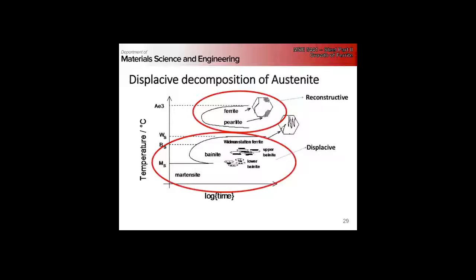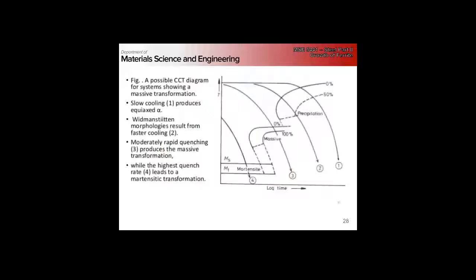So basically, we get this partitioning between reconstructive and displacive transformations, a separation between the nose of the TTT curves here. And if we look at the CCT diagram, here's the cooling rates.